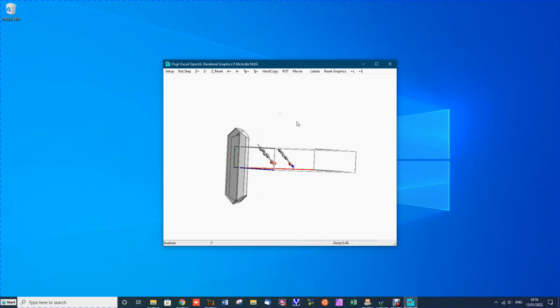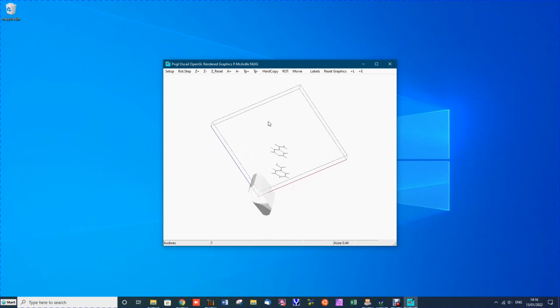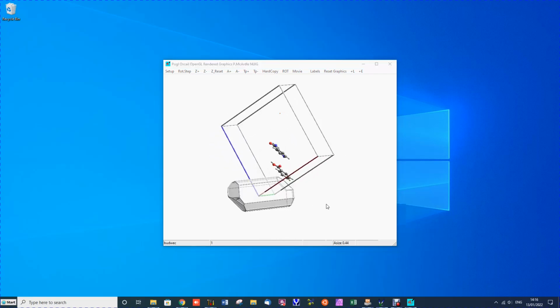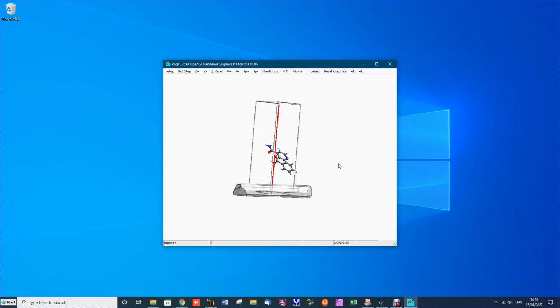Now the reason for preferred orientation is this elongated crystal shape. If we turn around the crystal so that it's lying down, we have the crystal orientated the way it most likely would arise in a flat plate reflection mode geometry setup.